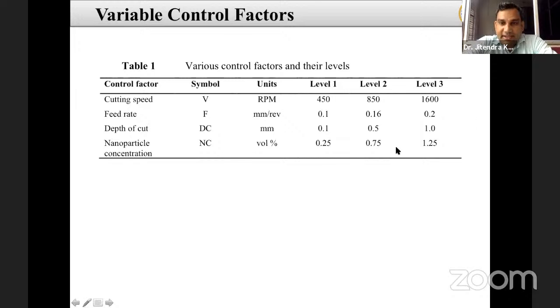So four variables, three levels. So this 0.25 is nothing but 0.125% graphite and 0.125% talc. So this is the 50-50% concentration of both nanoparticles in the coconut oil.